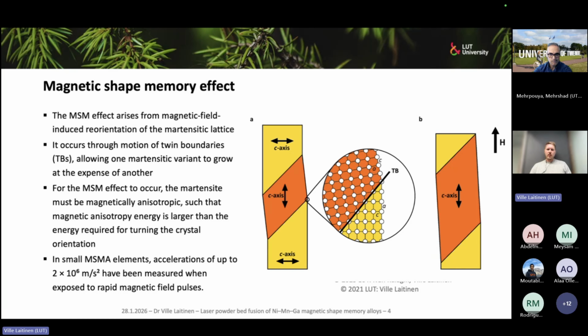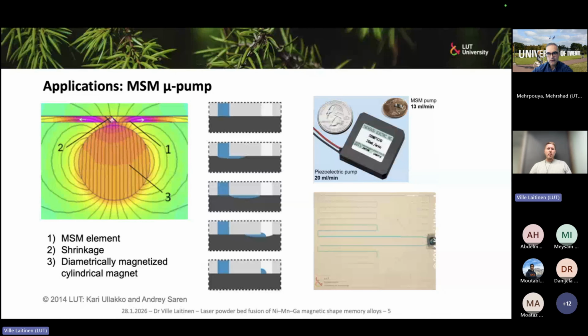Now, the main advantage of this is, of course, that this phenomenon can be very fast. So if you make a very small single crystal, you can achieve, in saturated magnetic field pulses, up to 2 million meters per second squared acceleration. So 200,000 Gs. That's the fastest material we have ever made. And extrapolating from this acceleration, it's possible to make actuators that can have 200 kilohertz actuation speeds or frequencies with the magnetic shape memory effect. I will also cover applications a little bit.